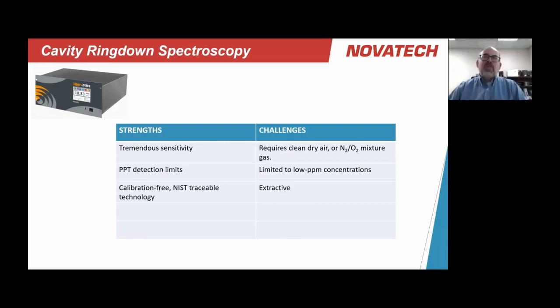From a challenge perspective, it does require a source of clean, dry air or a mixed gas of nitrogen and oxygen. And the technology, while it excels at very low concentrations, it doesn't work at higher ones. So we're limited to measuring at that very low end. And finally, as with many of the other ones, it is extractive. I have to bring the sample to the analyzer.